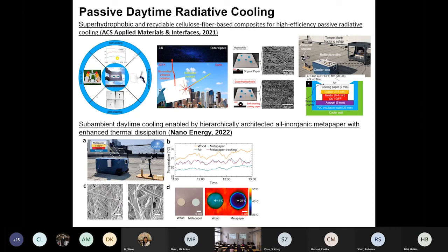Then we studied another type of paper, and we totally abandoned the use of organic paper and studied inorganic paper here. We relied totally on inorganic paper to design a cooling paper, and this cooling paper could achieve passive cooling. What is the idea? Actually, I just showed you. The surface has really high reflectance to visible light, as well as high emittance to infrared wavelengths between 8 and 15 microns, and this material itself has really good fire resistance.